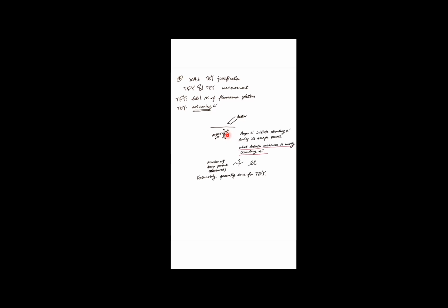Electrons do have a strong interaction. The consequence of that is the Auger electron will produce a lot of secondary electrons during this process. So this Auger electron is consumed, and it will produce a lot of secondary electrons. It's a cascade of electron production here. And in fact, what enters mostly in the detector are the secondary electrons, not the original Auger electron from the decay process of the sample. So we do see there's some detail in this process.